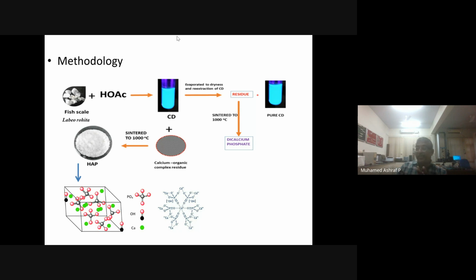That is also important. Generally, you will get an off-white or somewhat light, off-white bluish color. Here we are getting very pure hydroxyapatite, and this is the structure of that. And then again, this filtered solution contains carbon dot. In this carbon dot we found some crystals, so we reduced the volume and evaporated it to dryness, and then we found good crystals of calcium salts, and we took those out.